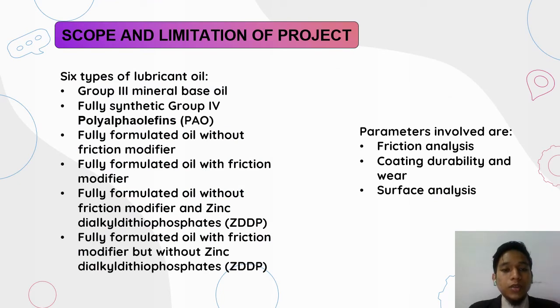There are 6 types of lubricant that involve Group 3 mineral base oil, fully synthetic Group 4 PAO, fully formulated oil without friction modifier, fully formulated oil with friction modifier, fully formulated oil without friction modifier and zinc dialkyl dithiophosphate, fully formulated oil with friction modifier but without zinc dialkyl dithiophosphate. And the parameters involve friction analysis, coating durability and wear, and surface analysis.